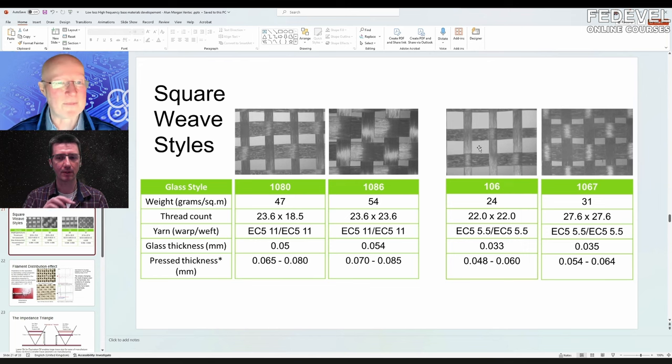Sometimes people rotate the designs. So it just goes diagonally? Yes, and that is a good technique for mitigating the problem. So you end up angling this around by 15, 20 degrees, whatever. So in the end, both parts of the differential pair see the same basic image. The problem with that, of course, is you're having yield losses and costs. And also there can be some influences when you don't have the weave square with the panel. There can be some dimensional stability issues as well. The material can move around in unexpected ways with temperature cycling. So it is a solution, but not a perfect solution.